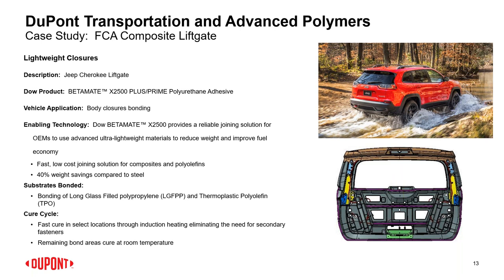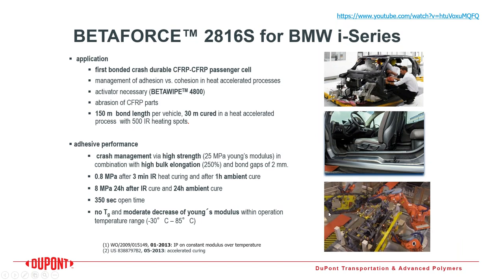Can you go back one slide? I just have a quick question. No problem. The last one. It says 3 minutes of IR heat curing and after 1 hour of ambient cure. So is that... that will be full cure? Yep. And so after the 1 hour, you get the 0.8 MPa, right? In full cure, in 24 hours, you'll have the 8 megapascals. Okay.